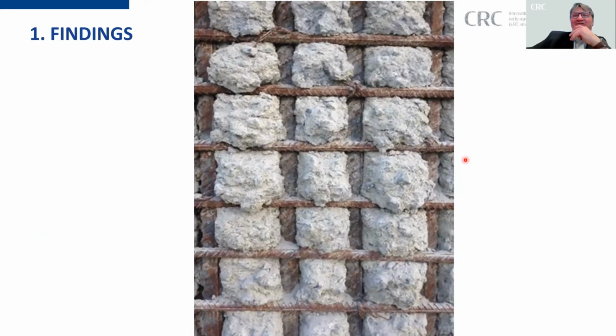This picture is provocative, but with high performance concrete, you have a low water binder ratio, so you obtain a sticky and viscous concrete. And due to the fact that the ratio of reinforcement increases, you obtain a very dense reinforcement. So the mere error during the placement leads to a catastrophic situation, which obviously jeopardizes the initial objective.